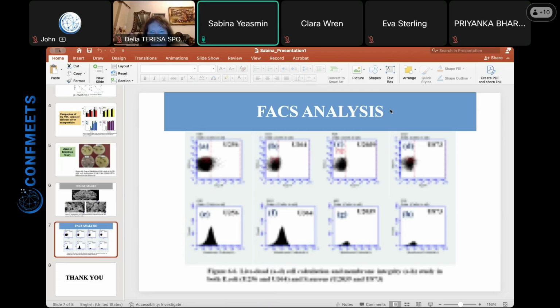So from the zone of inhibition study, from MIC value and from bactericidal activity value, and again from the SEM images and from FACS analysis, we can conclude that the silver nanoparticles I have prepared, 13.6 nanometer, 22 nanometer and 42 nanometer, have great bactericidal activity, and can be used as an antibacterial agent in comparison with the drugs where we get resistant bacteria. We can use it as an ointment in future, as silver nano ointment.